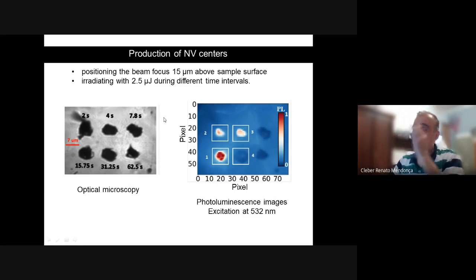So what we did is we tried to generate those NV centers in given positions inside diamond. So here are the positions where we irradiate with femtosecond lasers with different illumination times. And in the end, what we got is this luminescence. When we excite at 532, which is green light, the diamond doesn't fluoresce. But if you have the NV center present, it shows some fluorescence. Those pictures here are actually the fluorescence of the NV center.